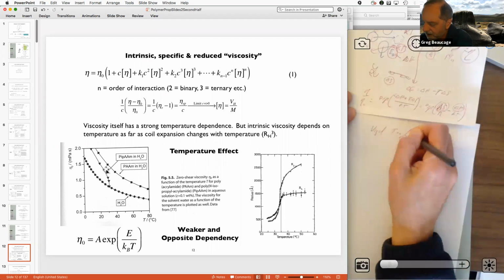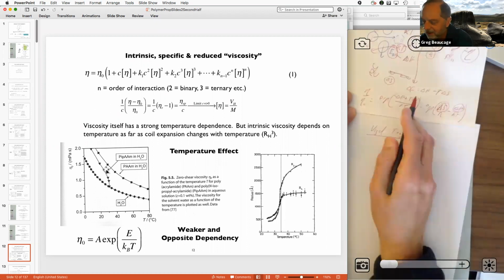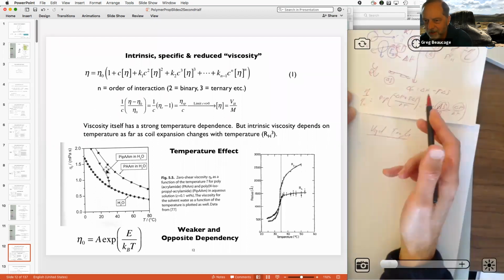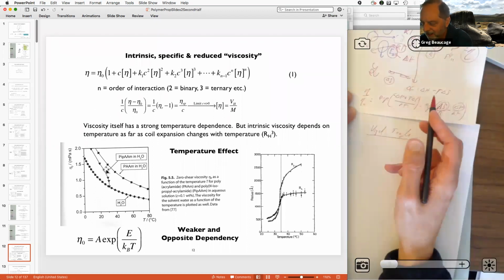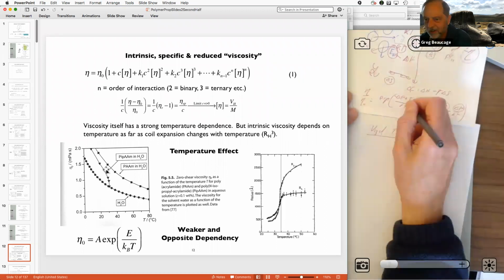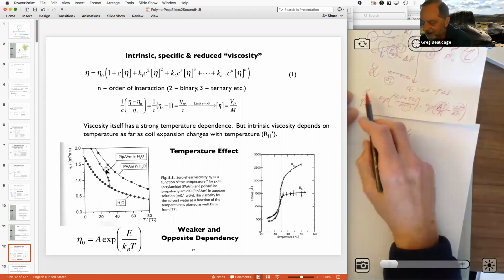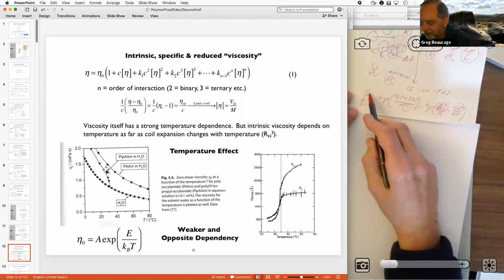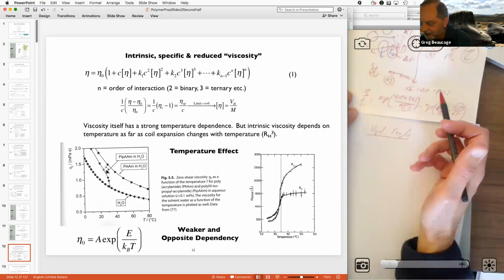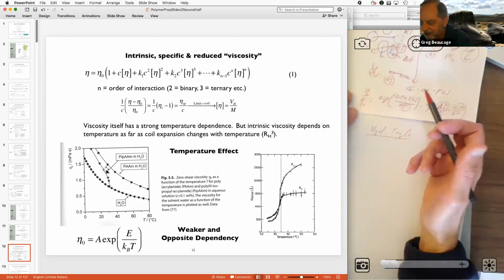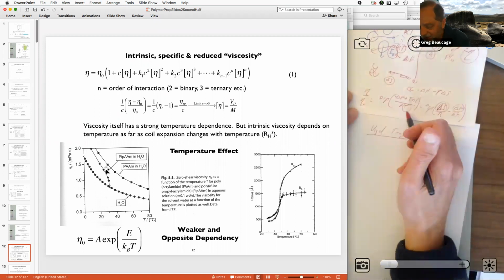In a polymer, you have a glass transition, and it doesn't flow after that. Or you could have some other temperature, like crystallization, where flow stops. So this absolute temperature that's based on zero is a zero number for flow. When you reach temperature zero, the viscosity goes to infinity, because this becomes infinity, and exponential infinity is infinity. So at zero temperature, it becomes a solid. But things can become a solid before 0 Kelvin.